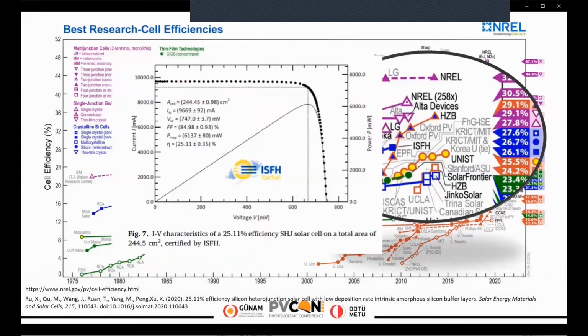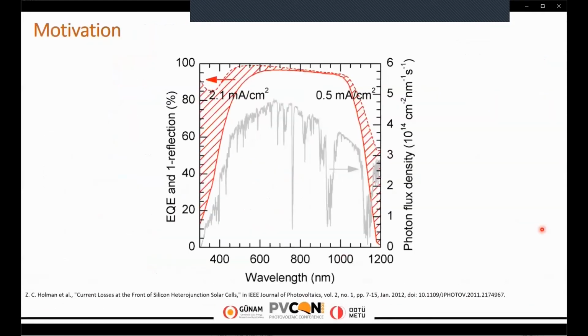Recent developments show that over 25% efficiencies could be achievable by bifacial silicon heterojunction solar cells with relatively high fill factor values. In the figure, you can see quantum efficiency and 1-reflection results of silicon heterojunction solar cells. The research was done by Holman in 2012, and they mainly focused on current loss mechanisms of silicon heterojunction solar cells. On the rear side of the solar cell, the current loss is around 0.5 milliampere per centimeter square, and on the front side of the solar cell, the current loss is 2.1 milliampere per centimeter square.